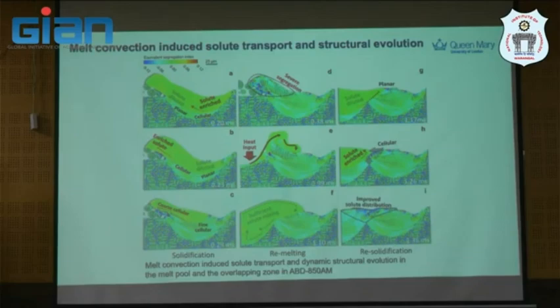So the planar growth proceeds to grow this way, and the cellular structure actually becomes penetrated here. This makes this region enriched. So you will see that the enrichment of the solute is related to cellular growth here. And then you get an improved solute distribution. That means if you print more and more, but still, in some cases without care, you will trap some solute, and that's what we call solute trapping.